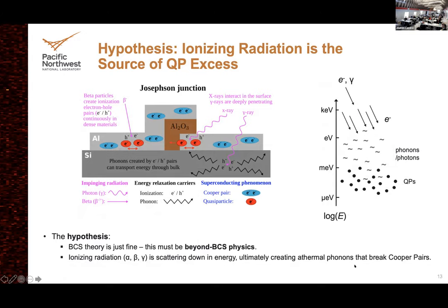Here's a qualitative cartoon of our model. We don't yet have a good microscopic quantitative model. Radiation from the environment — beta plus, beta minus, x-rays — arrives at the device. Charged particles can interact directly in thin layers of superconductor and break Cooper pairs — that's fairly well understood. Low-energy x-rays do something similar. Higher-energy x-rays tend to penetrate the thin superconductor layer, interact in the silicon substrate, make phonons, shower down to phonons that permeate the device, couple back into the superconductor, and still have enough energy to break Cooper pairs — it only takes less than a millielectron volt to do that, and we've got keV-scale energies coming in.